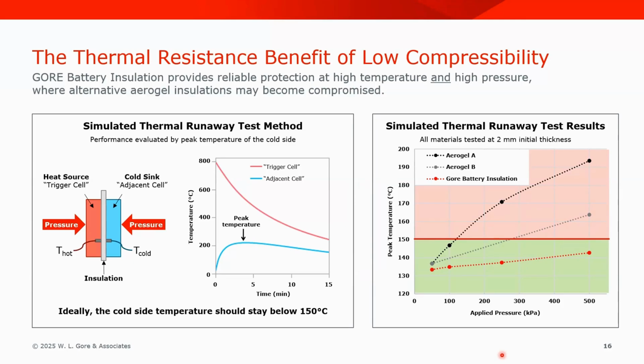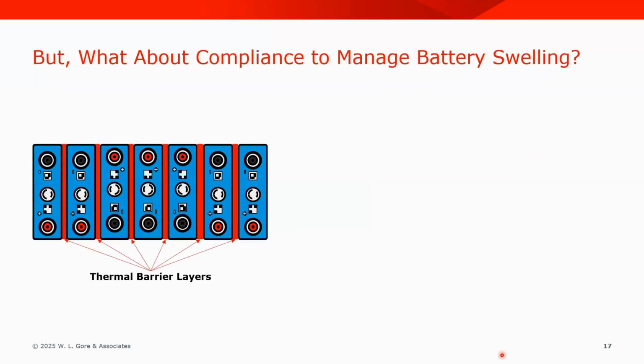So we can measure this in the lab, and we can also measure it in real time. But what you might be thinking at this point is, what about compliance? Because as I mentioned in one of the earlier slides, compliance is necessary to manage battery swelling. And if the GORE battery insulation is a low compressible material, how can we manage that second job? Well, it's pretty simple. And what some of our testing partners have done is to simply replace some of the thermal barrier layers in the module with compliant layers.